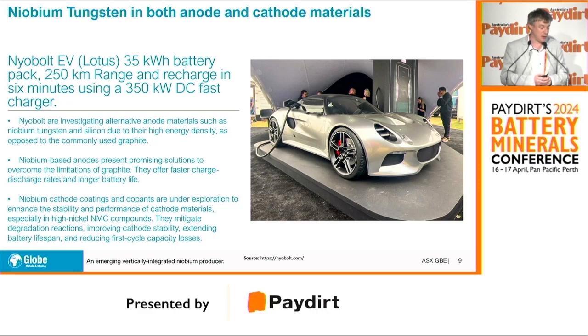Nyobolt in the UK have developed, together with Lotus, the EV, which is a 35 kilowatt-hour battery pack, 250 kilometer range, and recharge in 6 minutes using a 350 kilowatt DC fast charger. So this battery contains a niobium, tungsten, and silicon anode material, as opposed to the commonly used graphite. In addition, it's also working on a niobium cathode coating to ensure stability and performance of the cathode material, especially in high nickel compounds.